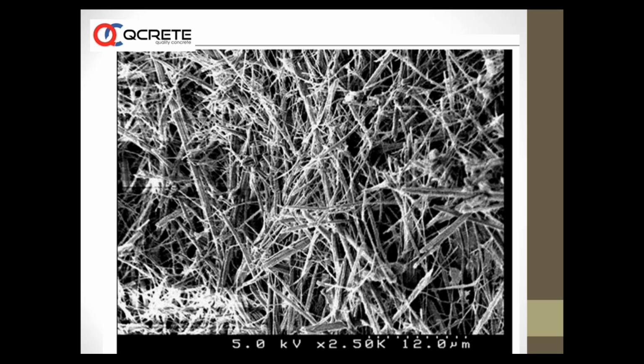So be rest assured, with the use of these materials along with cementitious materials, the strength and properties go on increasing as the concrete ages. This crystallization continues for a longer and longer time, as long as some unhydrated cement particles are there, some moisture is there, and some calcium hydroxide is there—this process and the growth of crystals will continue. They pack the capillary pores, density increases, and impermeability increases.